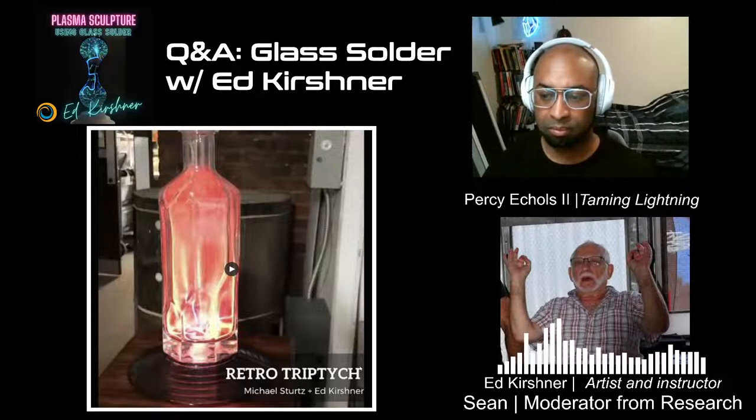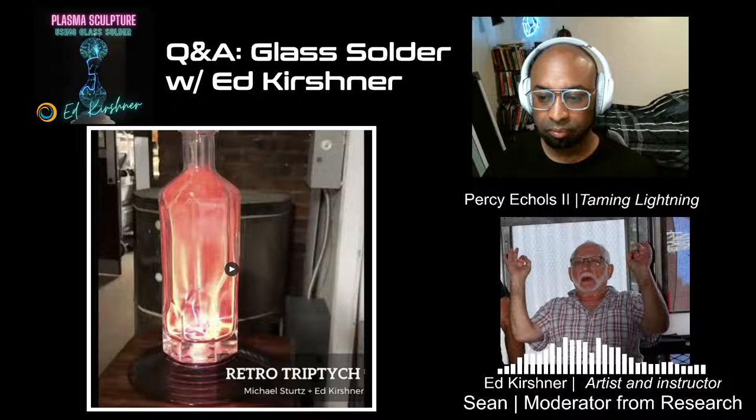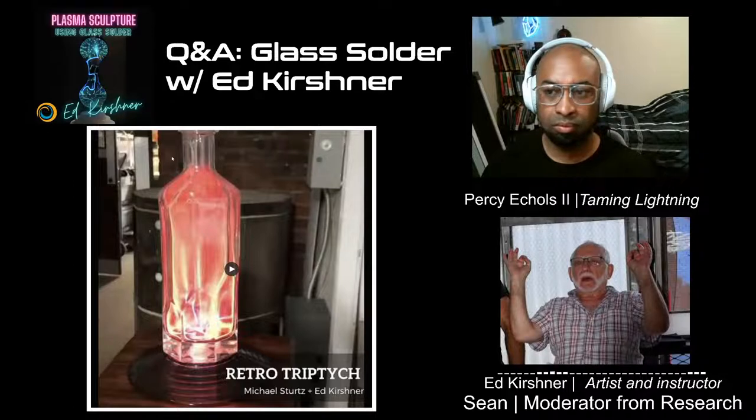Now, sometimes there are little differences with the different pieces of glass and with different types of studio glass, so it's an alchemy to it. After a while, you get to understand how to do it without a problem. You have much less of a problem with the manufactured glass on slumping. That's a trade-off. It's tougher to put the electrodes on, but you almost never have a slumping problem with the manufactured glass. It's harder, and it seems to have a higher annealing point. So the soldering is done significantly below the annealing point.